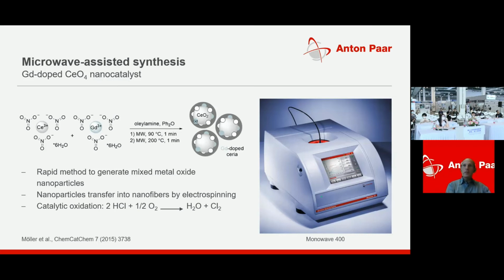So you see, after 2 minutes, we have received our nanoparticles, which makes this microwave-assisted synthesis very distinctive and characteristic for its rapid preparation of novel materials, with a significant yield, and with the option to scale up the preparation from some milligrams to even kilograms of product.